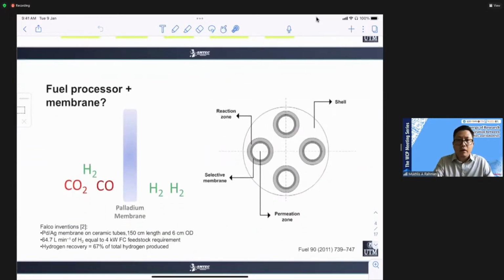So the idea of incorporating a membrane into the fuel processor was actually addressed by Falco in 2011. Falco developed a fuel processor incorporated with a palladium membrane to further purify hydrogen. But Falco used a ceramic tube with a length of 150 centimeters and 6 centimeters OD. What he got is a hydrogen production that can supply a fuel cell with 4 kilowatts. The recovery of his membrane is quite good, 67% of the total hydrogen produced. Let's say 100 moles of hydrogen produced, the system is able to separate up to 67% of it.